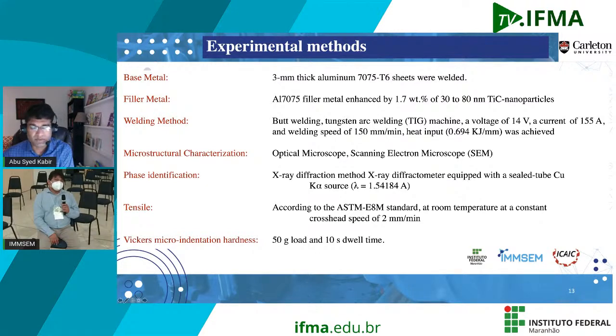Then we did some microstructural characterization with optical and scanning electron microscopy. We did phase identification with XRD, and we did the tensile testing and the micro indentation hardness testing.